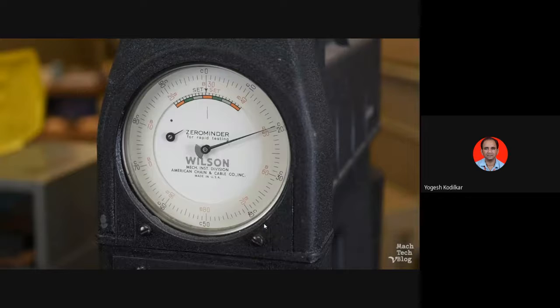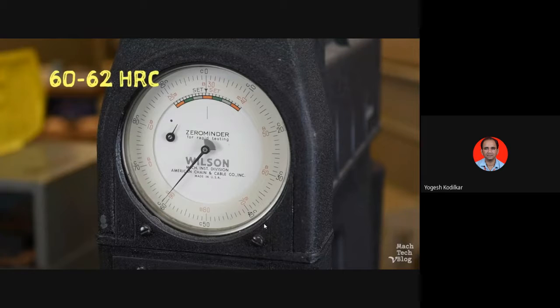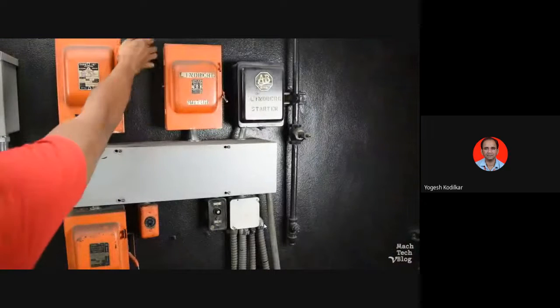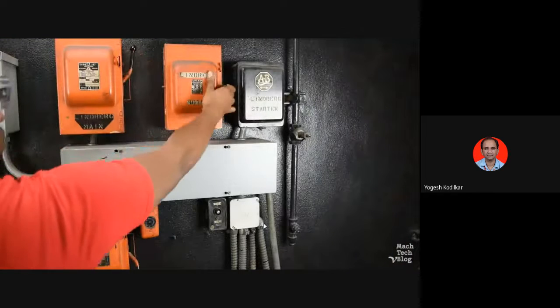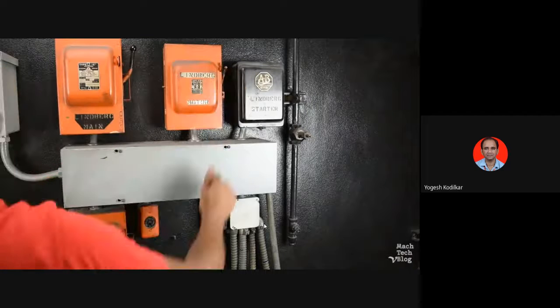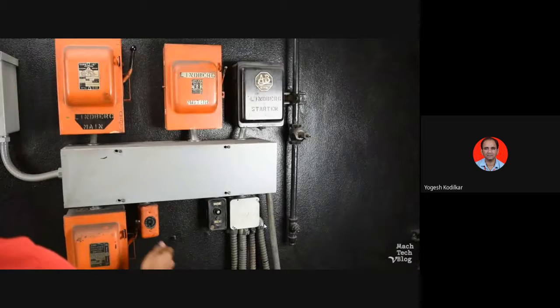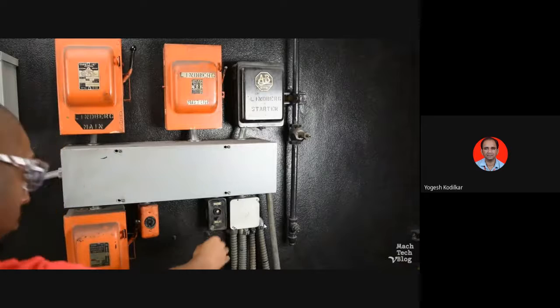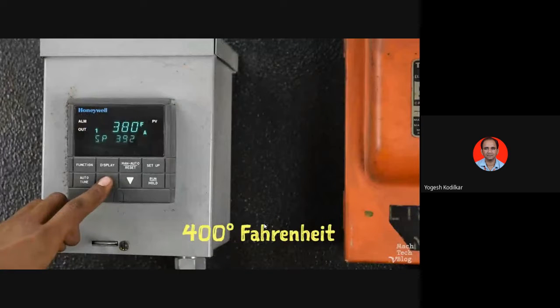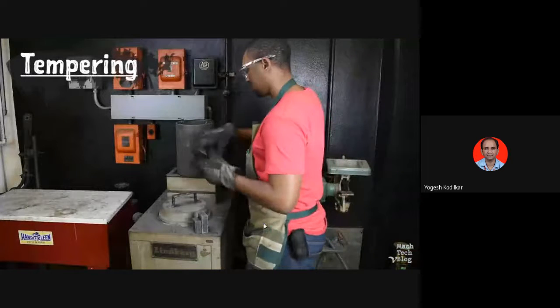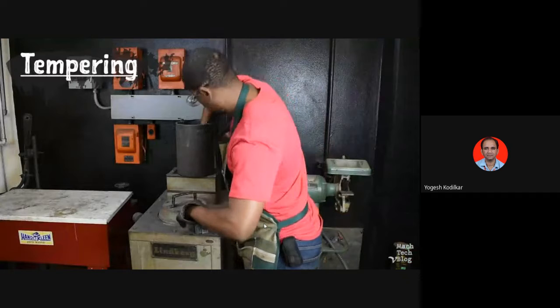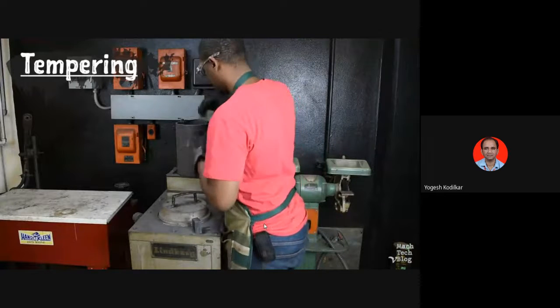Martensite is very hard stuff indeed, but the harsh process of quenching leaves a lot of internal stresses in the steel. And that's why it's common to stress relieve quenched parts by heating them back up to a relatively low temperature and holding them at that point for some amount of time. So let's go ahead and heat up the draw furnace to 400 degrees Fahrenheit. Place the parts in the basket and lower them down into the furnace. Make sure to replace the lid.